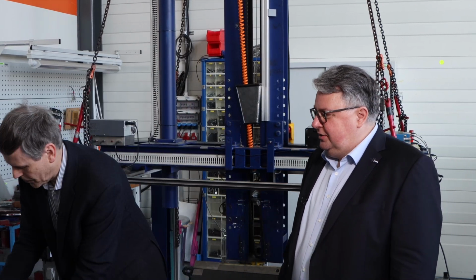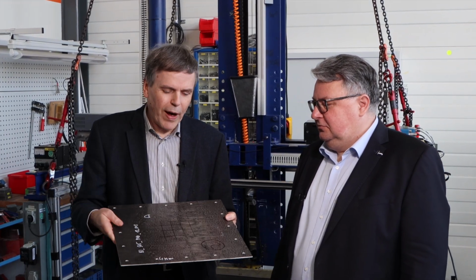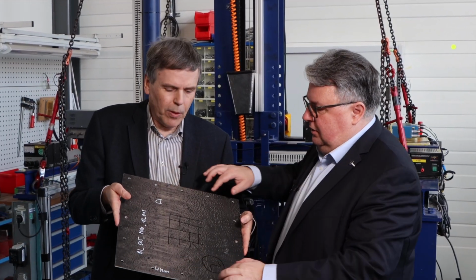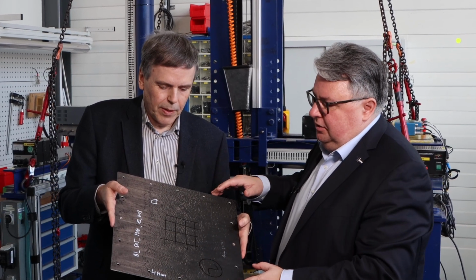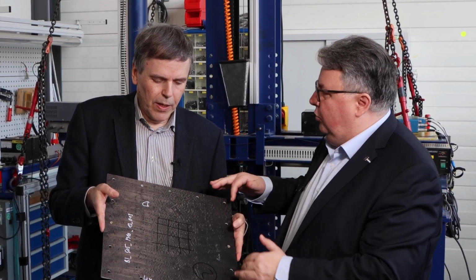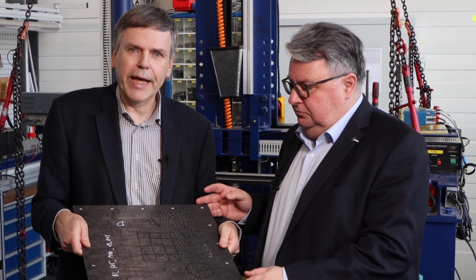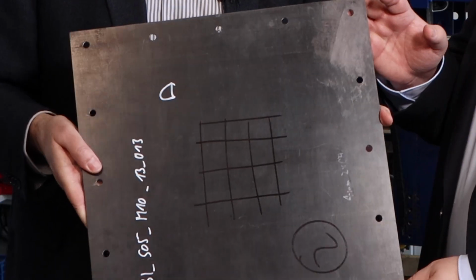Yeah. So you have a part here. Maybe you can show it. The plates that we are testing are quite large plates, but still quite handleable. This is a rectangular, and it's a normed shape. It's always the same shape, right? Yeah. It's 40 by 40 centimeters, and it's bolted along the edge to really clamp it, so when you impact it, you have the same stress levels, tensile stresses, out-of-plane stresses, as you would have in a real bottom protection plate.